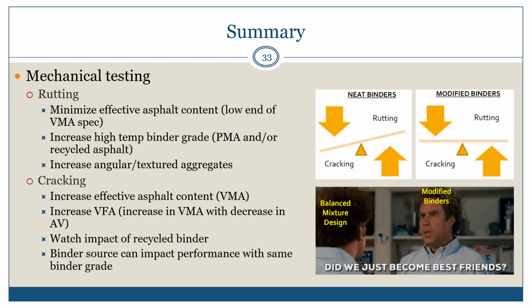And consolidating all of our interviewees' responses to our 2 days worth of questions. If we really want to go ahead and make some mixture adjustments to meet our rutting and cracking tests, this is what it comes down to. From a rutting perspective, you're going to have to think about minimizing effective asphalt content, maybe designing your mix at the low end of the VMA specification. You're going to look to try to increase your high temperature binder grade, whether that's utilizing polymer modified asphalts or additional recycled asphalt in the mix, and ensuring that you're getting good angular and textured aggregates in that material to ensure that you're getting adequate shear resistance internally in that mix is going to be critical.